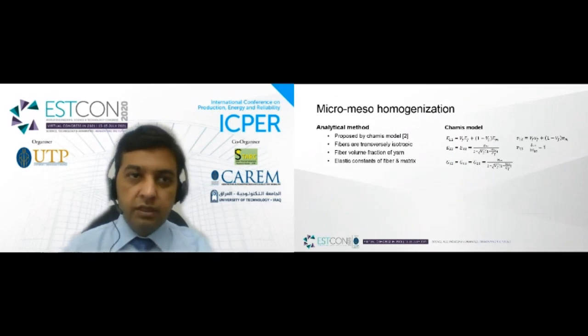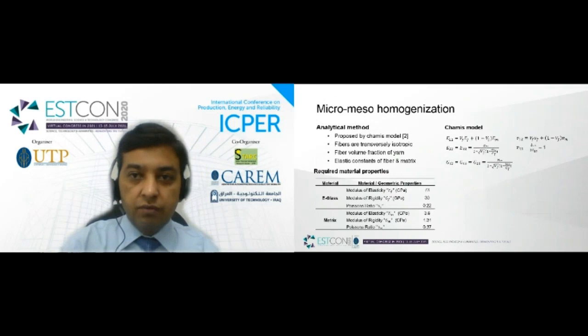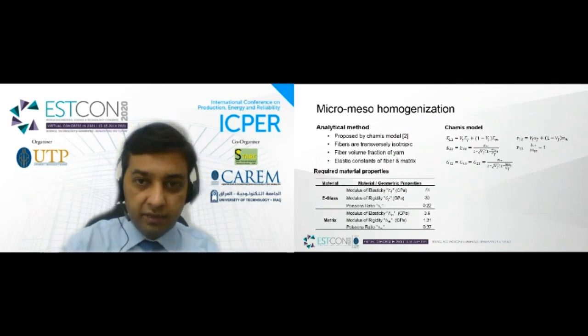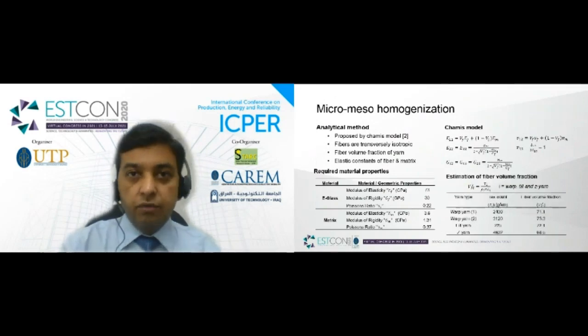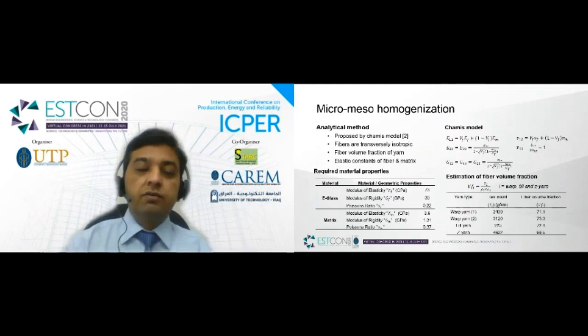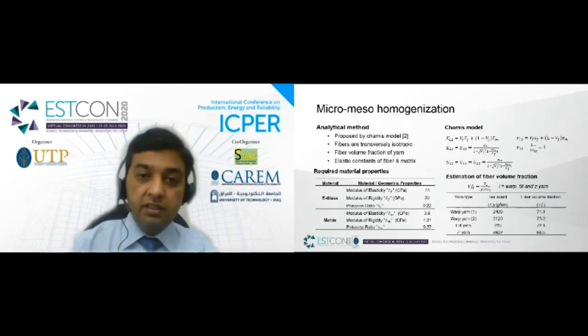So now in case of micro to meso homogenization, the analytical method used here is based on the Chamis model, which requires the elastic constants of fiber and matrix and their fiber volume fraction in impregnated yarns. The elastic constants of e-glass fibers and epoxy matrix are summarized in the table on the left, whereas the fiber volume fraction of impregnated yarn is estimated based on the weave parameters of the 3D fabric, which is the tex count. The tex count is the linear density of yarns in grams per kilometer. The estimated fiber volume fraction along with their tex count is listed in the table.